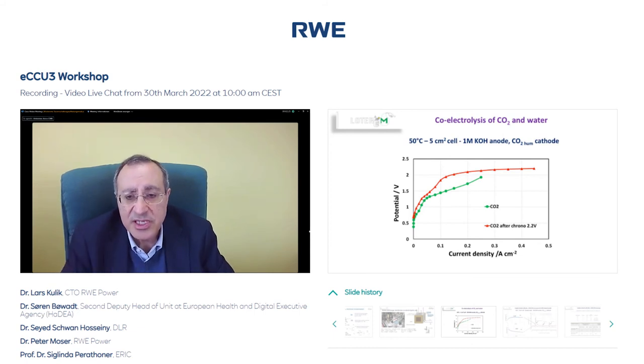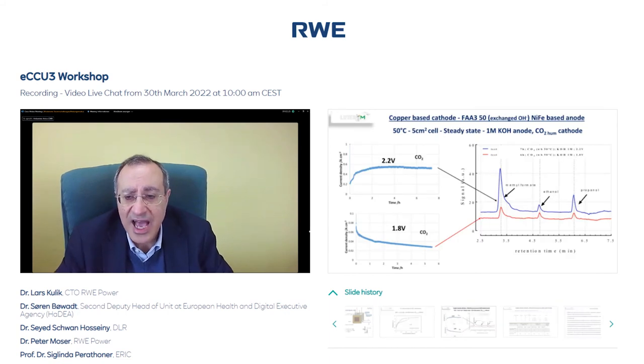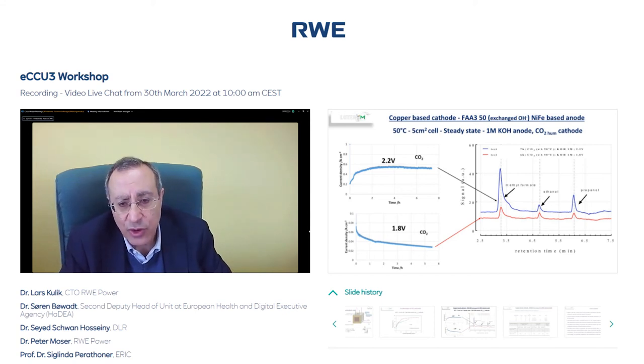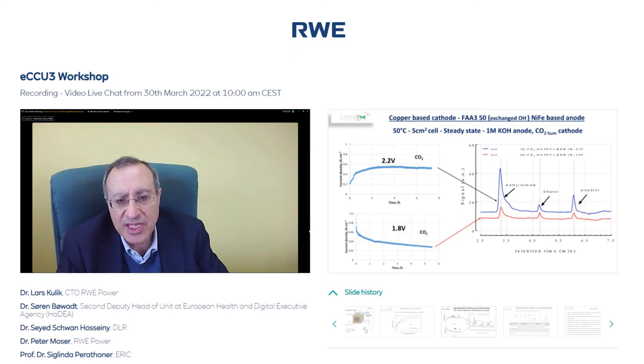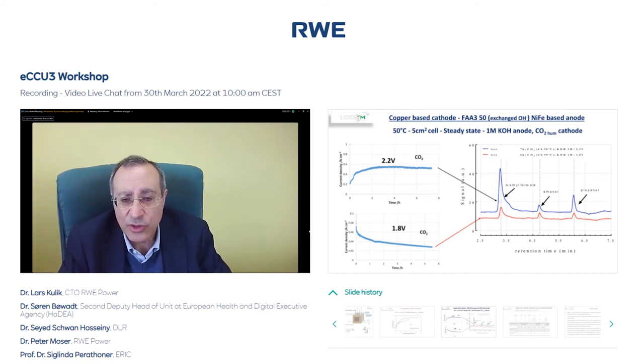This was also discussed by Simon in the previous presentation, but I want to emphasize in slide number 17, please, that when we operate the cell under voltage control at, let's say, a constant voltage of 1.8 volts, this is the overall cell voltage, cathode plus anode and membrane, we have a decrease of current density with time due to the adsorption of CO2, the poisoning blockage effect by CO2 on the catalytic sites. But if you move to 2.2 volts, we start with 200 milliamperes per square centimeter, and during operation, we can achieve 600 milliamperes per square centimeter.